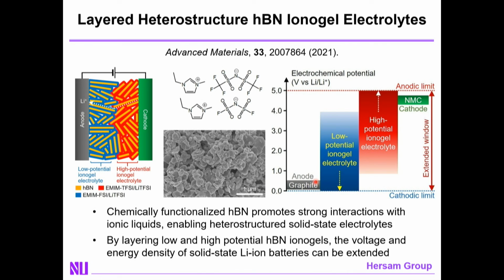So you may think to yourself, well, why don't you just change your ionic liquid? And you can do that. And if you change your ionic liquid, you can reach the low potentials of graphite, but then you compromise the high potential range. So the delta V is still only 4 volts. This is why ionic liquids never made it in lithium-ion battery commercial setting.